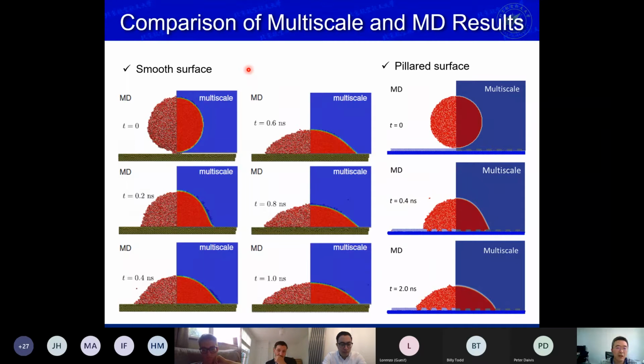So now we show the results. The left side is our pure MD simulations, and the right-hand side is our multiscale simulation. After we apply the slip boundary conditions in the VOF method, as you can see, the dynamic wetting process has a perfect match to the MD data. And this one is for the smooth surface. Even for the pillared surface, we can see that our multiscale simulations are also consistent with the MD simulations.